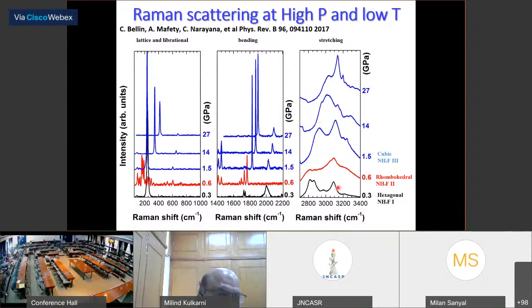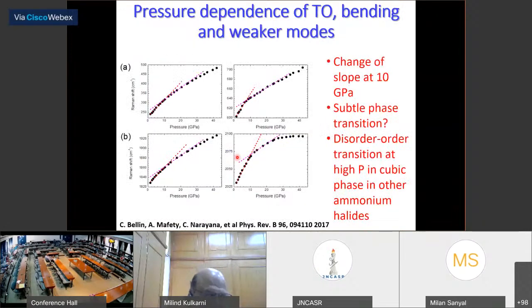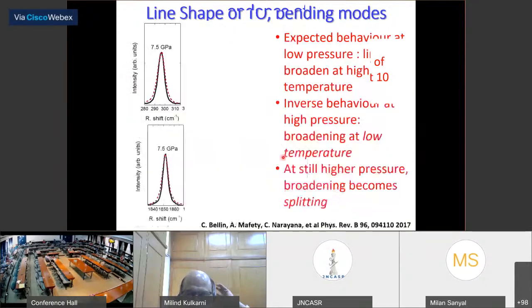Now, Raman actually shows three phases at different temperatures and pressures. You can see the hexagonal phase, then the rhombohedral phase, and the cubic phase. But once you start going into the higher phase, you start seeing a very nice change happening in the system. The Raman shows a discontinuity at around 10 GPa, and you can see a change happening in most of the modes. There is also a strong deviation after 20 GPa.